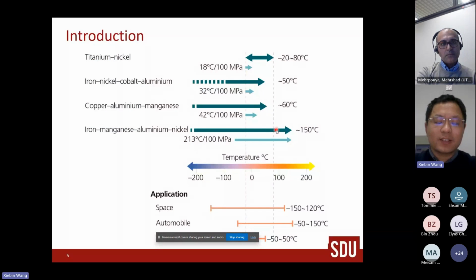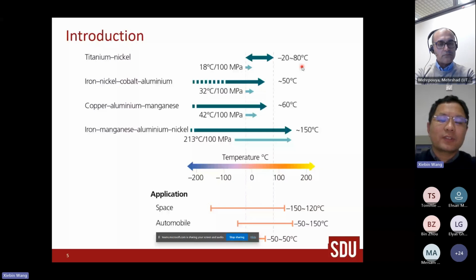Due to the unique properties, the shape memory alloys have been widely used in many fields, for example, medical parts like stents and staples. But the nickel titanium alloys can only be used in temperatures between about -20 degrees to 80 degrees, because the transformation temperature is in this range. Of course, there are other systems for shape memory alloys, like iron-based and copper-based alloys. But for the iron-based alloys, the shape memory effect and superelasticity are not that high. And for the copper-based alloys, normally you need single crystals. So the transformation temperature limits the use of nickel titanium alloys.